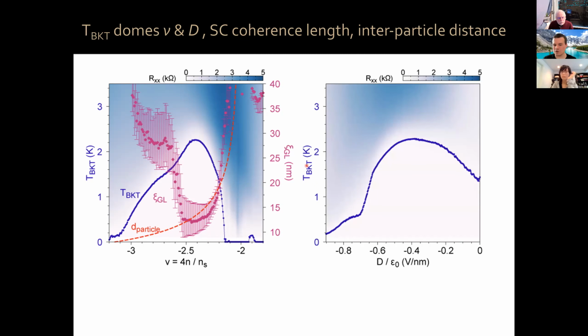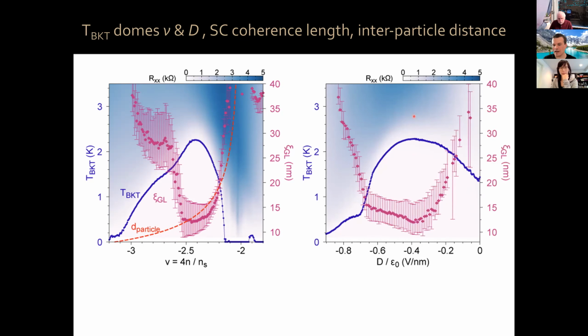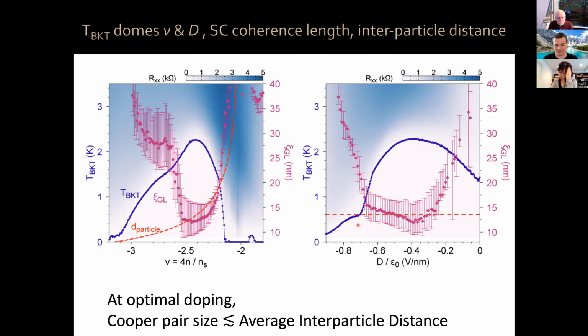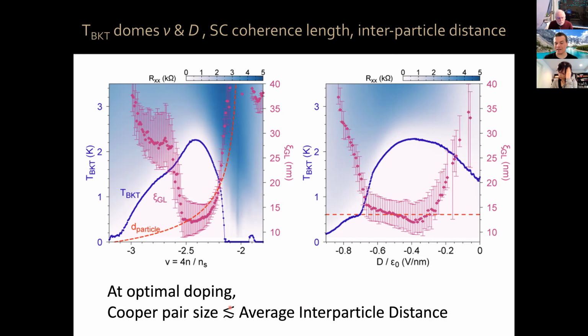We can also look at TBKT as a function of displacement field, and we can measure the superconducting coherence length. This is all at optimal doping, and this is the average interparticle distance at optimal doping. Now, in a weak coupling superconductor, your superconducting coherence length tells you your Cooper pair size. As you can see, at optimal doping, your Cooper pair size is less than or equal to the average interparticle distance. In the strong coupling regime, it's not so clear that you can interpret it in this way, but if anything, it's an upper bound.